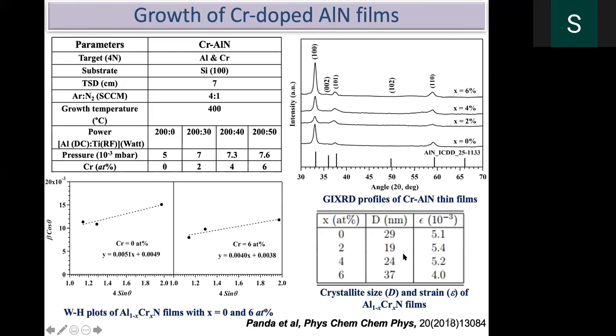When you see the grain size, this 0 means pure aluminum nitride. When you add chromium, the grain size increases. One can understand that from the width decrease and the intensity increase. From this we can understand very clearly.